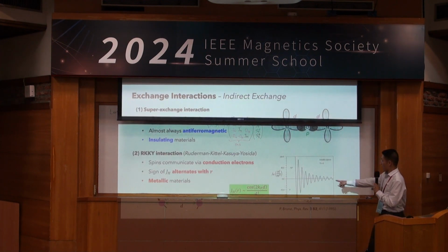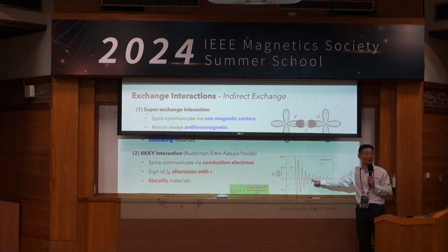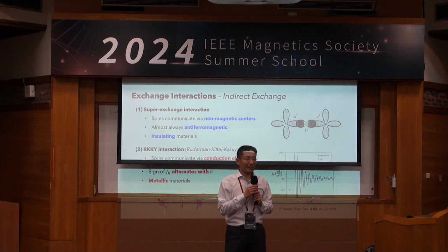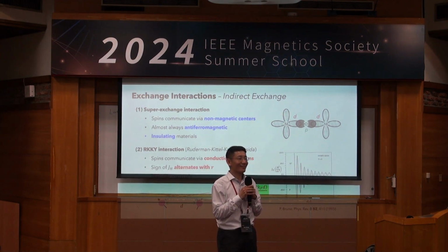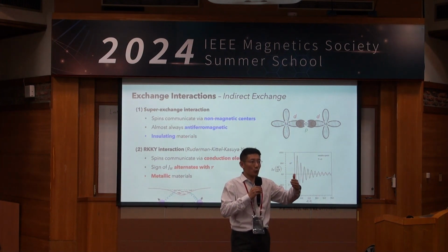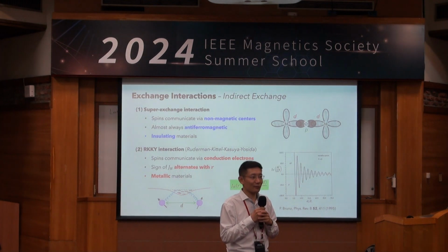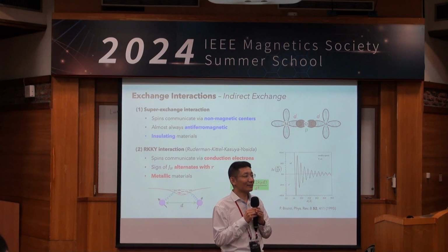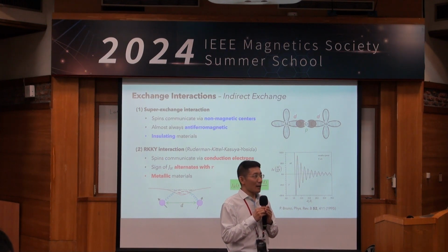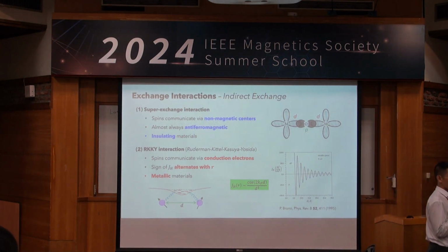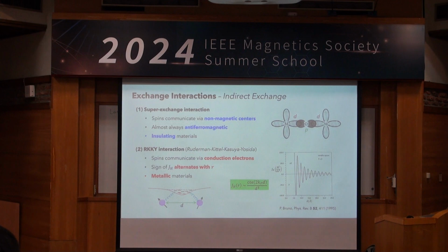So you are asking what happens if I stand right on the turning point, right? That's a good question. The system becomes magnetically very unstable at that point, because an infinitesimal perturbation on the lattice will result in a substantial change of the magnetic ordering. Okay. So the spin's orientation will be random at that point. Is it correct? Yeah, the system has the possibility to suddenly turn from an antiferromagnet into a ferromagnet, or vice versa, if you could prepare the system right on the point.